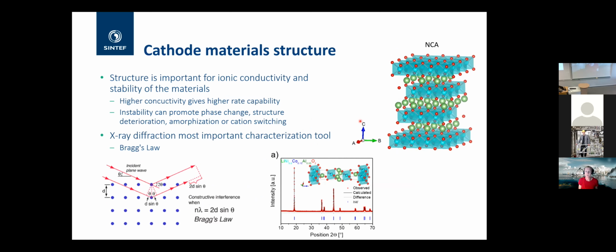The cathode material structure is extremely important to understand, to be able to understand how lithium-ion batteries behave, both their lifetime, their capacities, and so on. Obviously, higher conductivity of the lithium ions also gives you higher rate capability, meaning that you can charge and discharge your battery faster without losing performance. Structure can also explain instabilities and promote phase change. You can have structure deterioration. Sometimes you have amorphization, or also something that's called cation switching. The latter is prominent, for instance, in the NMC materials, where the lithium tends to switch places with the nickel. And in doing so, you block further lithium diffusion in the structure. So it's very detrimental to the structure.